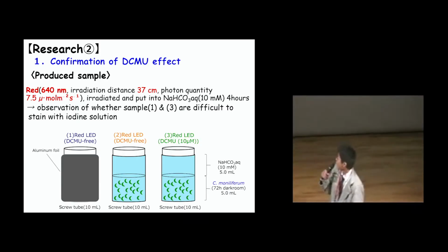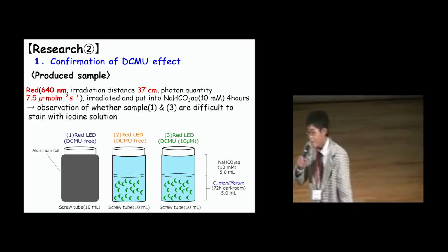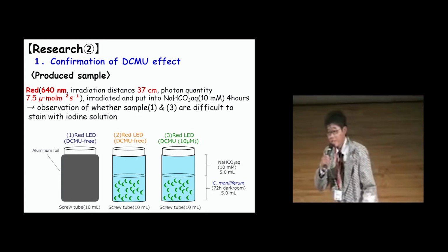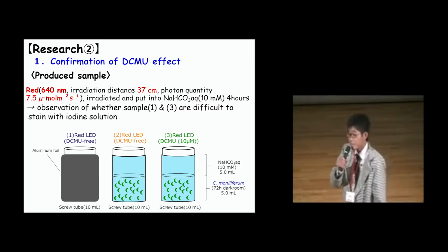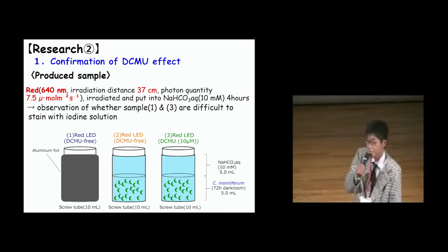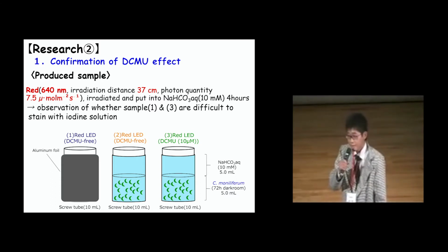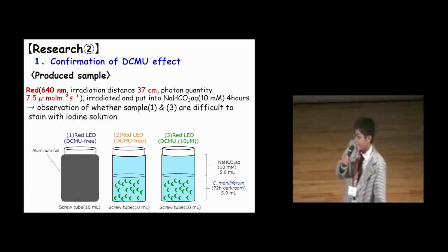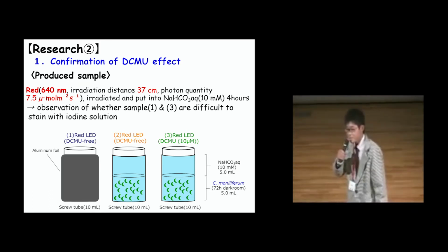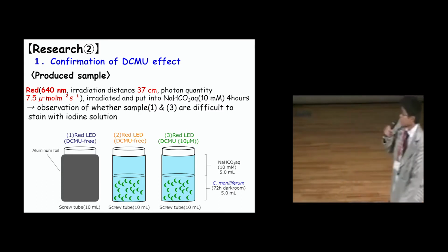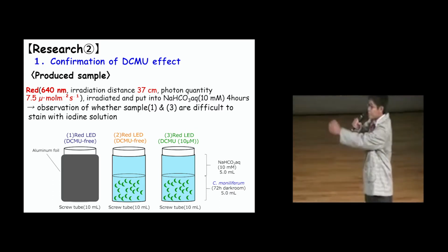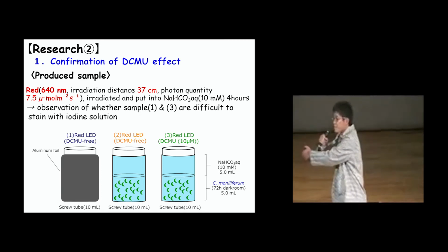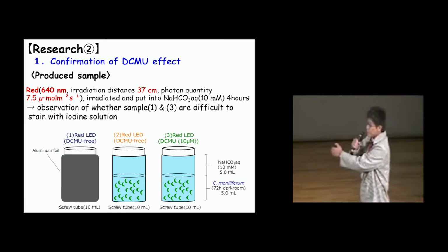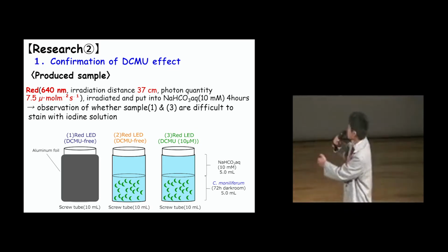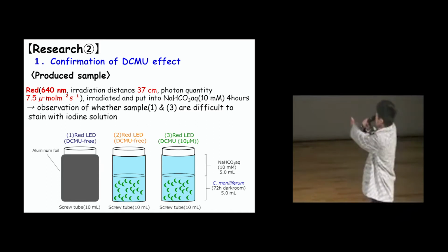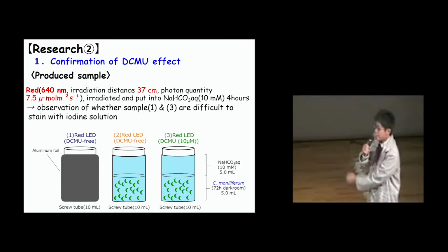Main result 2. 1. Confirmation of DCMU effect. Then we checked whether DCMU really showed an effect on Closterium moniliferum before observing with SEM EDX. We produced samples. Sample 1, wrapped in foil to prevent red LED, and no DCMU. Sample 2, red LED is added with no DCMU. Sample 3, red LED is added with DCMU.